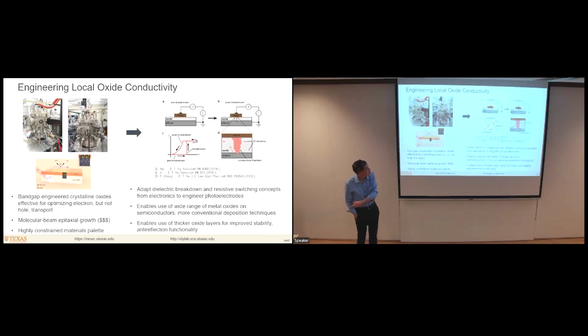Now, it turns out that at the same time that we were doing some of this work, there was another project going on in the group where we were looking at what's called resistive switching in metal insulator semiconductor structures. This is a behavior where, through the application of some appropriate combination of current and voltage, you can have changes in the vertical electrical conductivity of these structures by orders of magnitude. This occurs through the formation of conducting filaments through the oxide, which can be several tens of nanometers thick, basically through the assembly of oxygen vacancies.